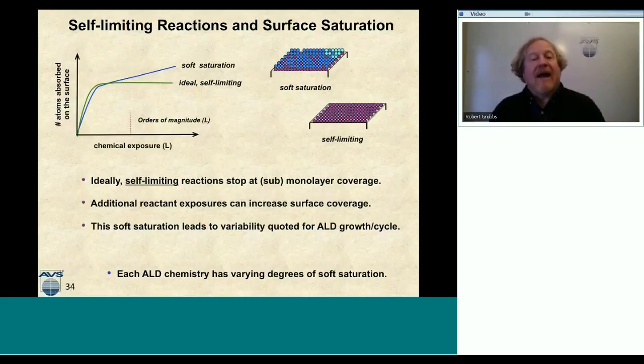So if you're running your ALD with a lot of chemical precursor, depending on what the precursor is, you could be somewhere up in this soft saturation zone, and you'll quote a different growth per cycle, per ALD cycle, than somebody else. And so for some chemicals, it's an order of magnitude difference up here in the soft saturation, and other times it just could be a factor of 5. So one of these chemistries is hafnium oxide. I know that hafnium oxide has a relatively soft saturation. So if you add a lot more chemical precursor, you'll probably start to fill in some of those reactive sites on the surface with a lot more chemical exposure, and then you'll get more atoms on the surface, which will give you a greater growth per cycle.